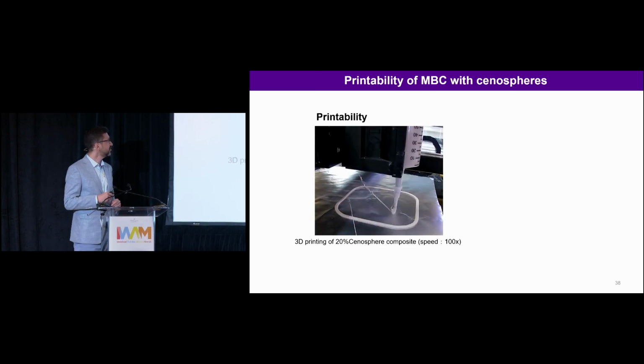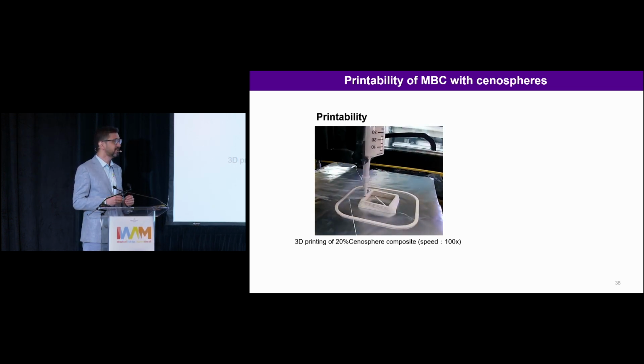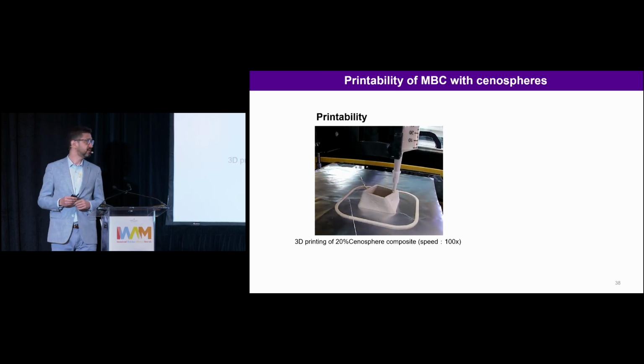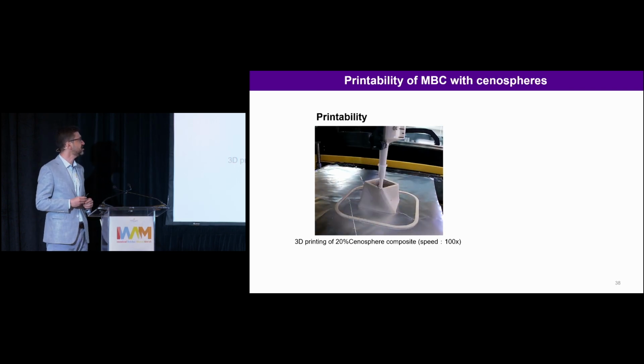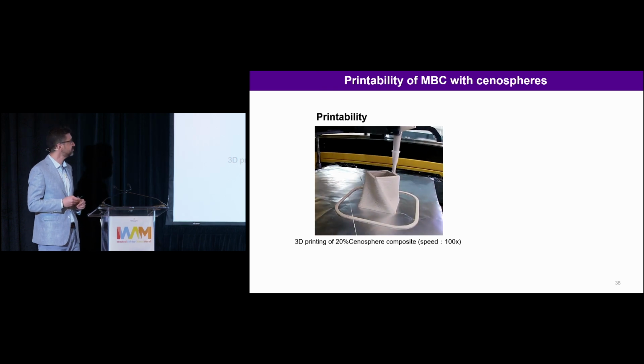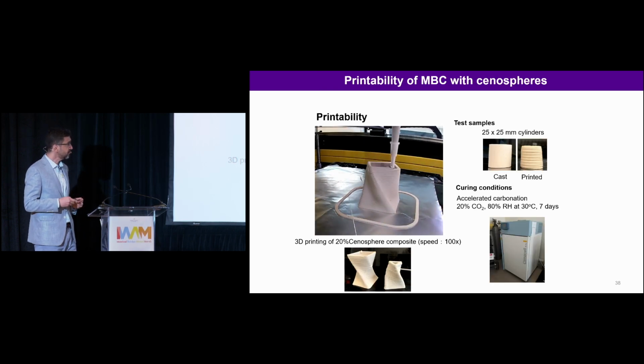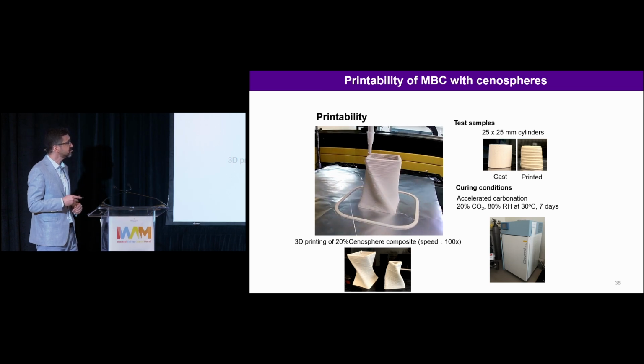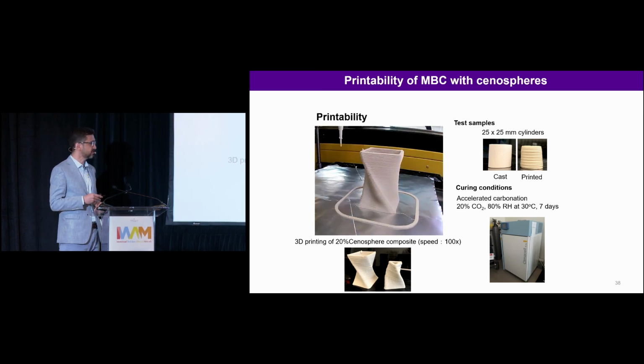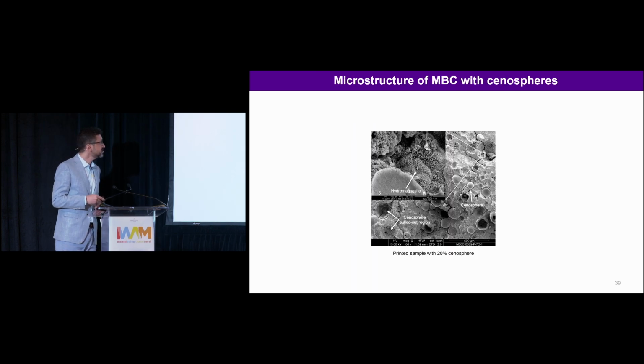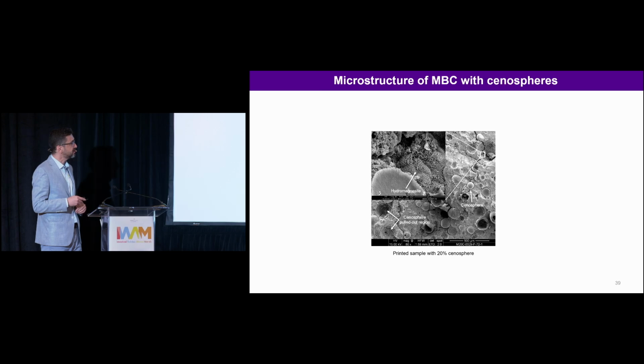So we look at the 3D printability of this magnesium-based cement, adding 20% cenospheres and some PCE-based chemical admixtures, and we are able to 3D print this material with intriguing shapes, and we also compare the printed versus cast samples, curing in this accelerated carbonation condition. And as I mentioned, cenosphere is a byproduct of coal combustion power plants. These are hollow, inert materials, and here we see some of them, and some of them are pulled out after testing, and we are also able to see hydromagnesite minerals in the microstructure.